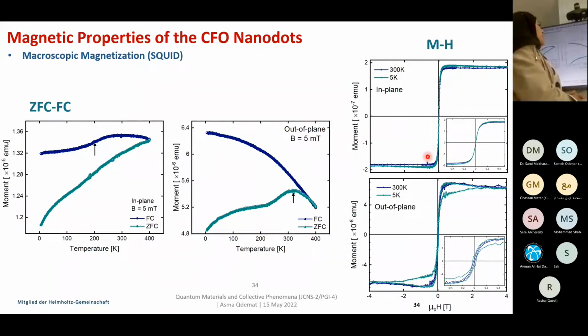And for out of plane, we can see that at room temperature it shows a superparamagnetic behavior with some very small hysteresis, as we can see here in the inset. And at 5 Kelvin, it also shows superparamagnetism with a very small hysteresis, and also an extra opening obtained at high and low field, which is due to the net magnetization between the two sublattices of the cobalt ferrite. So furthermore, for this system, we performed polarized neutron reflectometry in order to study the magnetic